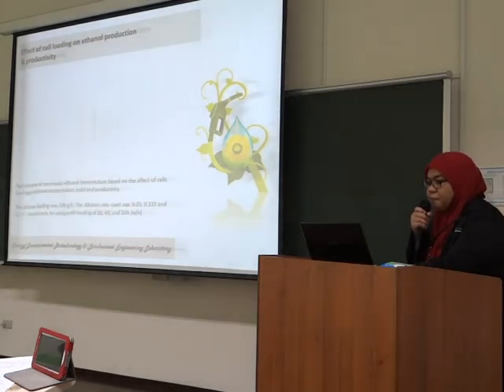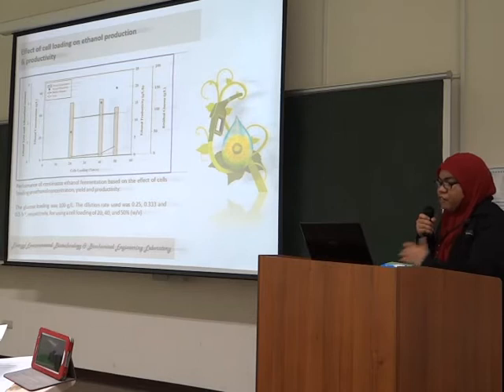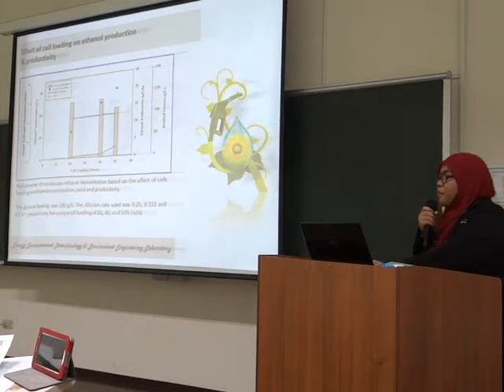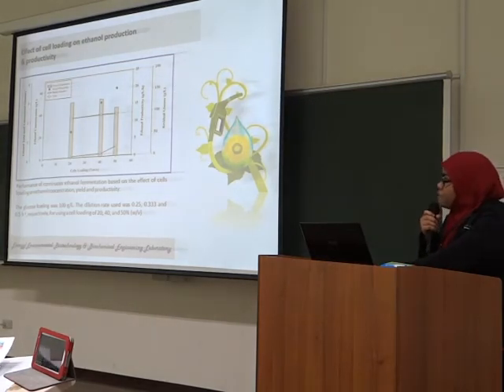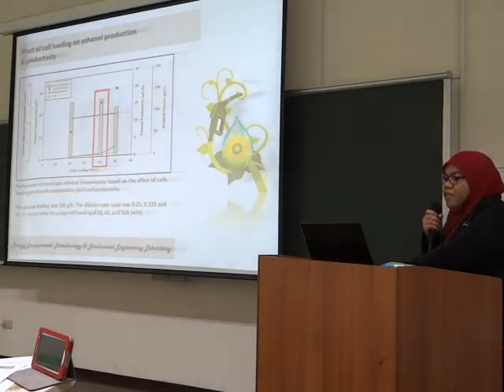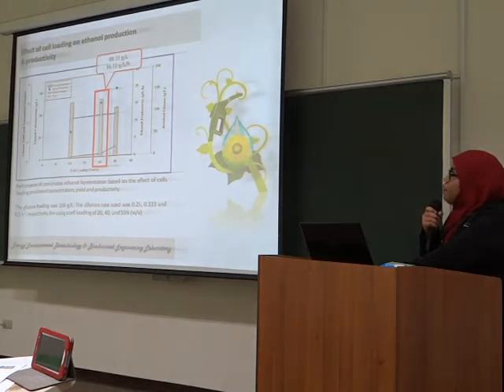And the second one, I tried to investigate the effect of cell loading on ethanol production and productivity. So I tried to vary 20% weight per volume, then 40%, and then 50%. And in here, we choose the optimum one, 40% weight per volume, with the ethanol concentration 48.31 gram per liter and productivity 16.10 gram per liter per hour.